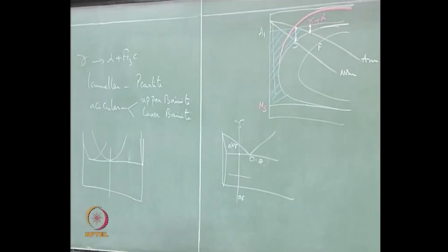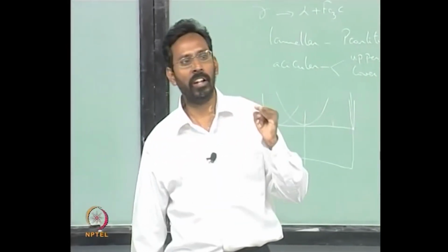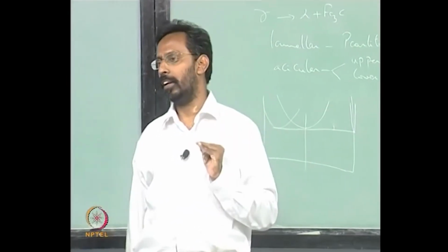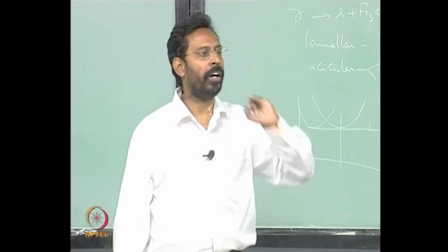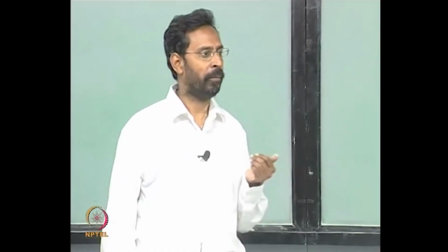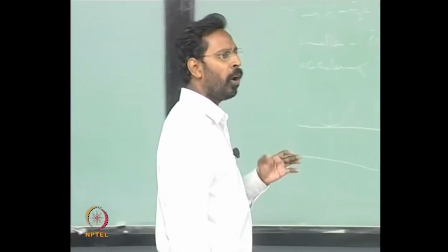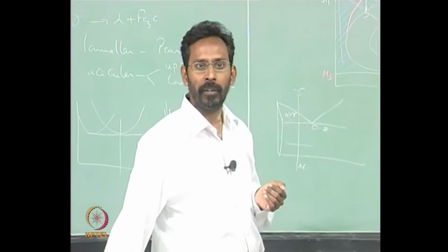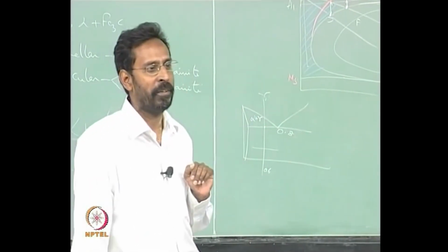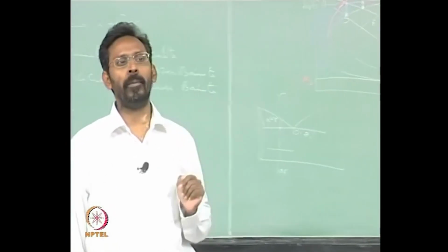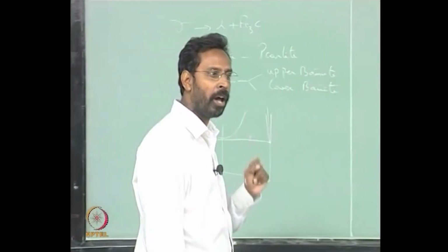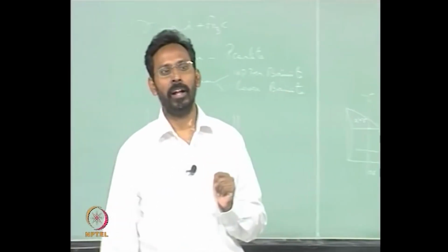So, colony size and the interlamellar spacing, these are the two basic differences that you see in a normalized and annealed steel. This is as far as it is a 0.8 carbon steel. The moment I make it 0.6, what will be the difference now? These two are anyway going to be there, whatever two differences that we just now talked about. In addition, something else would be different. The amount of proeutectoid phase is going to be smaller in a normalized case when compared to an annealed case.